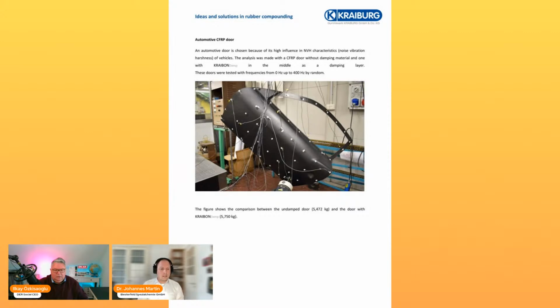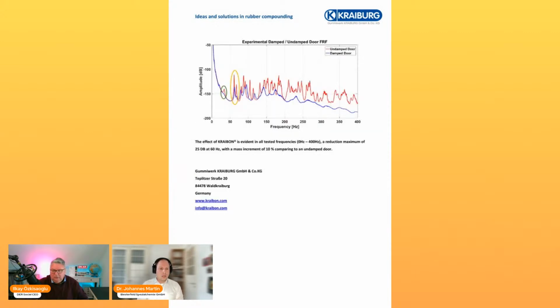And if you go to the next slide, Ilkay, you see the amplitude of this damped door, and you clearly see that there is immediately better acoustic improvement over the full range of frequencies, and in particular in the audible range for humans. You see at a frequency of, I think, 60 hertz, that we were able to reduce the sound amplitude by about 25 decibel.